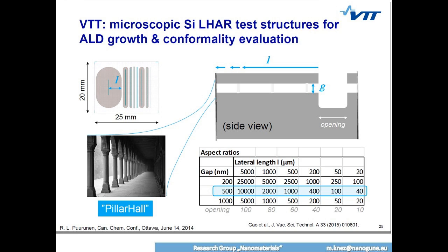There are methodologies now to produce chips. VTT does them, those PillarHall chips, where they etch a silicon structure and they etch it laterally. So you have basically a groove, and you have a channel below this groove where you can do ALD deposition, and the ALD coating, the precursors will go into this part here, and then they will diffuse. If you allow it enough time, they will diffuse along this channel here.